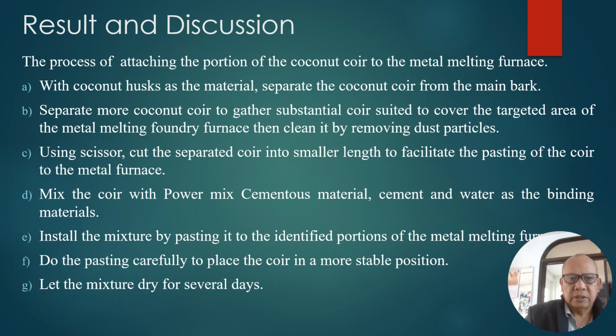The process of attaching the coconut coir to the metal melting furnace involves the following. With coconut husk as the material, separate the coconut coir from the main bark and then separate more coconut coir to gather substantial coir suited to cover the targeted area of the metal melting foundry furnace, then clean it by removing dust particles. Using scissors, cut the separated coir into smaller lengths to facilitate the pasting of the coir to the metal furnace. Then I mix the coir with the power mix cementitious materials, cement and water as the binding materials. Then I install the mixture by pasting it to the identified portion of the metal melting furnace.